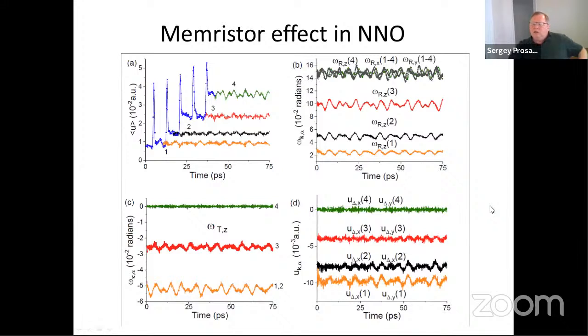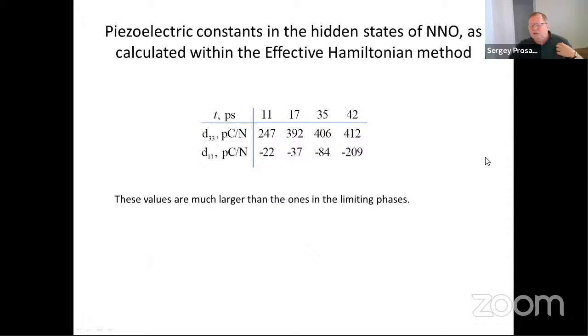So we see that actually these phenomena are rather general, because not only relaxors but also antiferroelectrics have these hidden states. To study these hidden states, we calculated the piezoelectric coefficients and found them extremely large. They are much larger than the coefficients in limiting phases.